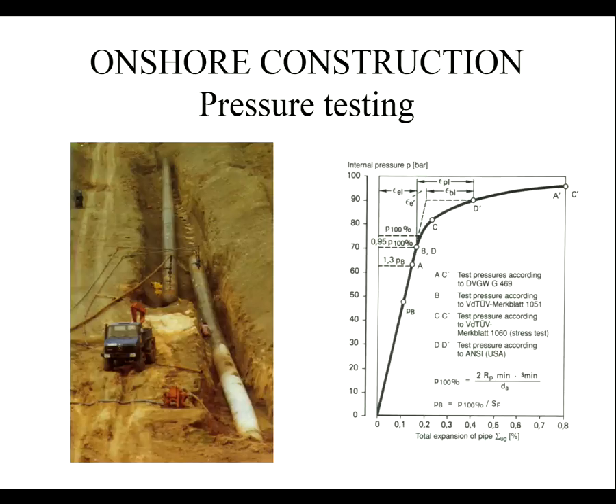The idea is that if you've got a distribution of defects in the pipe and in the welds, the higher you put the pressure, the bigger and bigger the defects are that actually run and cause failure. So at the low pressures, you're looking at enormous defects, and as you get up to higher pressures, the defects that will cause failure get smaller and smaller until it's got to a stage where you think that's not a critical size.